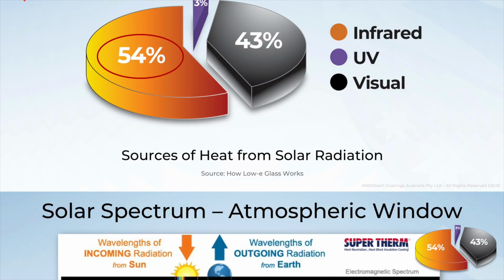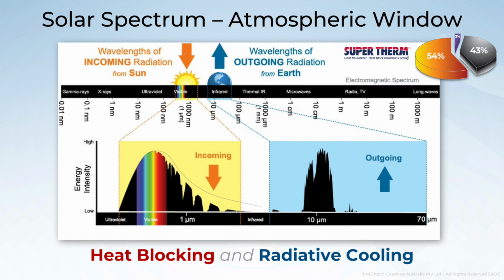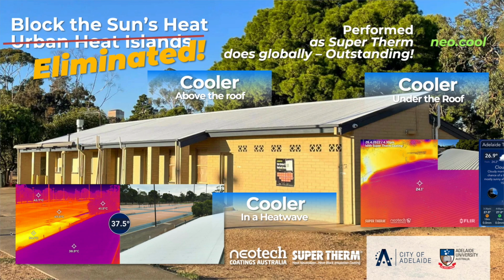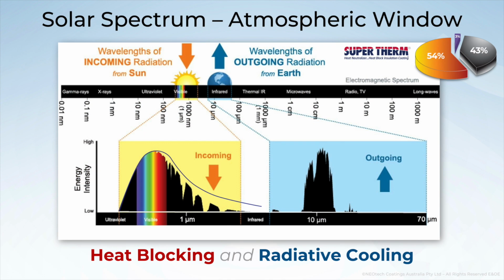When we look at the atmospheric window, we now know that 54% of the heat is from infrared heat. Well, Supertherm can block the UV, most of the visual, and pretty well all of the infrared heat, but it also heads back out as a radiative cooling because it goes out cooler than it comes in, and so it goes straight back into the atmosphere again. And really that's like the golden goose, the product that blocks most of the heat and reflects and returns most of the heat to the atmosphere as well. And as we'll see later, there was a study undertaken by the University of Adelaide. Supertherm demonstrated, as it does globally, it's much cooler above the roof.